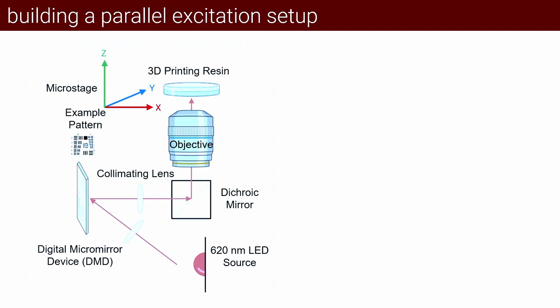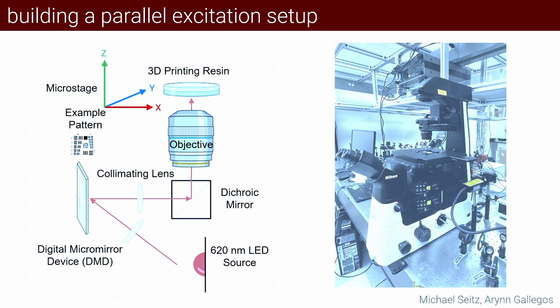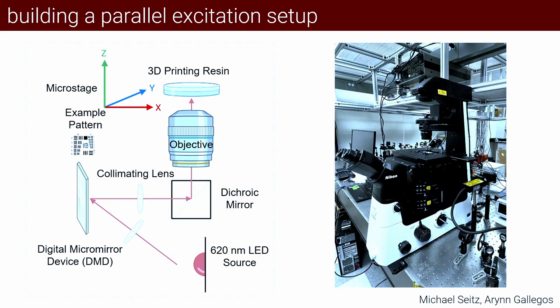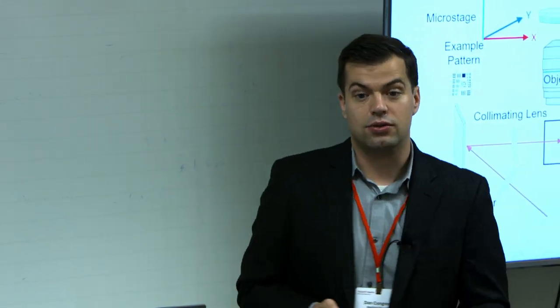And so here's the setup that we build. Basically, we can use a digital micromirror device here. This is in a lot of pico projectors. They're just tiny little microscale mirrors that flip and create an image. We can couple that into our 3D printing resin. And here's an image of that particular printer. This allows us to print, instead of one spot at a time, up to 2 million spots at a time. And so this gives us a really drastic speed increase.